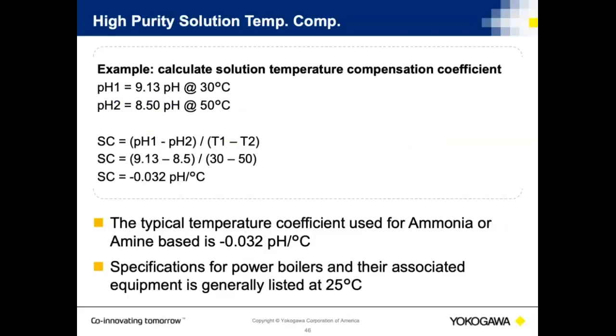These are an example. pH1, very easy to calculate the solution temperature compensation. You measure at one temperature, 30 degrees C, and it's 9.13 pH. You measure at a second, and it's at 50. The only key here is that those don't have to be precise values. It doesn't have to be precisely 30 and 50 degrees C. It just needs to be around 30 and at least a 10-degree differential to get a good representative value